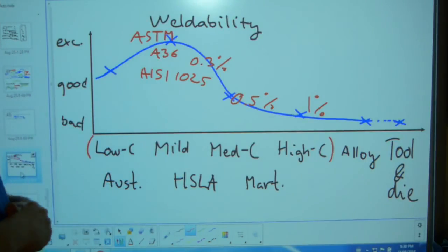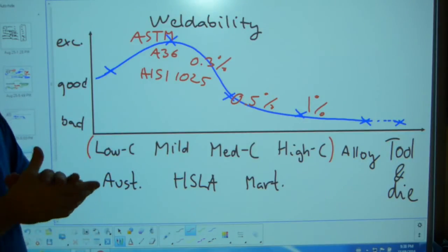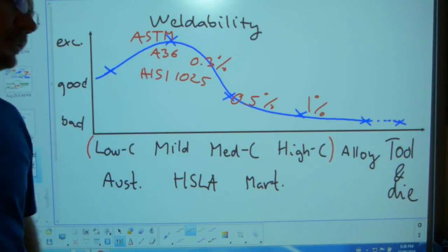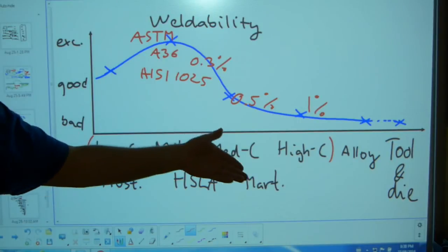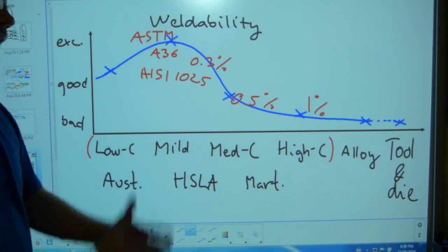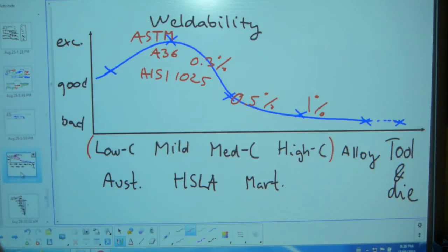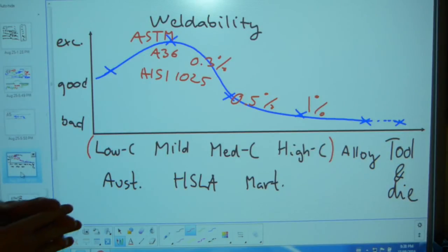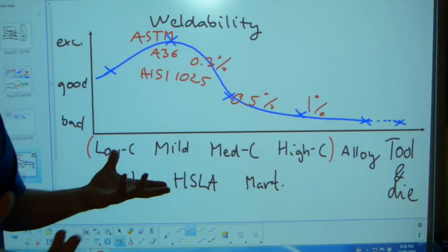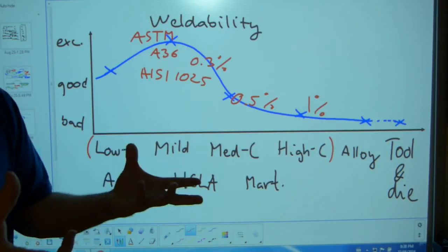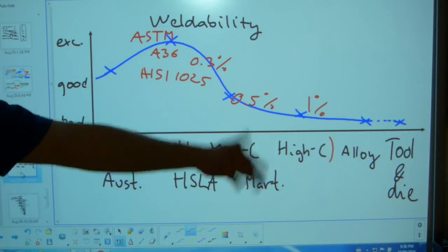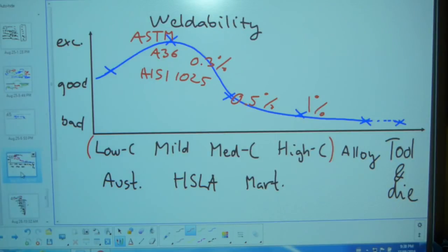That's another guy, and then from the machinist it comes back to heat treatment again, because it needs to be sharpened and honed. That's another process, and once it's done, it needs to be heat treated as well. So after it's been machined, it's quenched and tempered to the right surface hardness. Often they need to be case hardened, a differential hardening, where the outside of it and the cutting teeth have a different hardness than the shank of it. So that's why I placed tool and die steels over there. I'm not discriminating against tool and die steels. They are weldable, but it's a miserable affair.